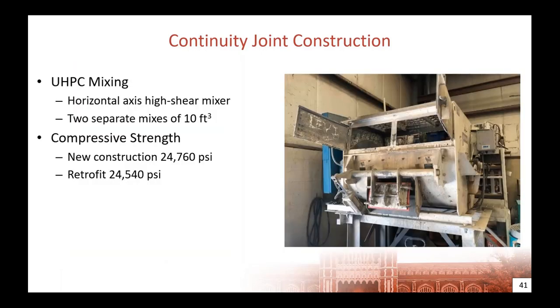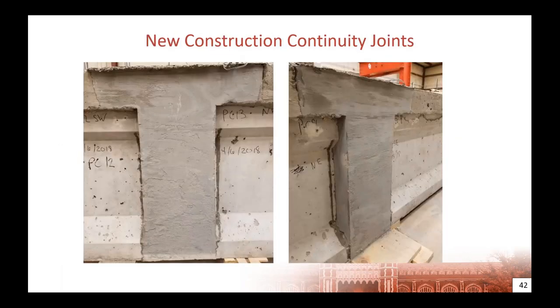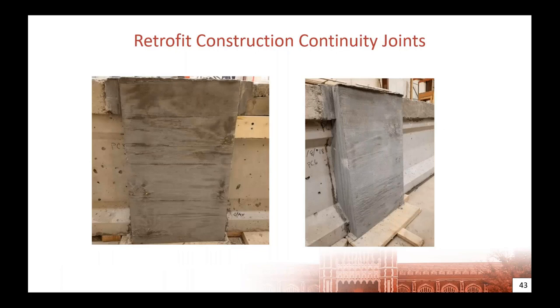For the UHPC, we used a commercially available UHPC product, so a proprietary UHPC mix that was mixed in our lab using this high shear horizontal axis mixer. It had a compressive strength of about 24.5 KSI for each set of joints. And these are some pictures of the completed joints. You can see a little bit of desiccation on the surface because of the formwork that we were using, but it didn't extend into the connection at all. It was just a surface consideration for this research.